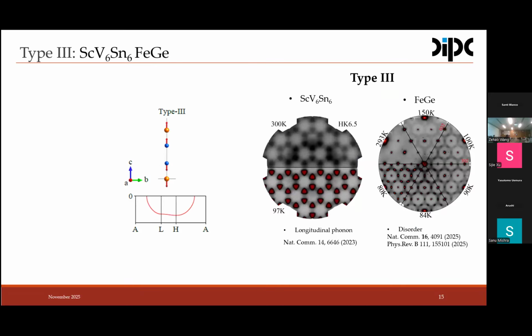So the first type of material I'm talking about is ScV6Sn6. As I said before, it's a type 3 charge order material. The diffuse scattering looks something like this, just to make the story short, in this HK 6.5 plane. It has some triangular shaped diffuse signal, which increases once we cool down. The other example is FeGe, which at high temperature has diffuse scattering, some hexagonal shaped charge precursors which condense at the M, L, and A points of the Brillouin zone.